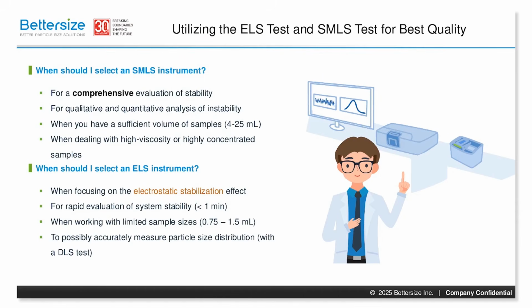SMLS is ideal when you have sufficient sample volume, typically 4 to 25 milliliters, and when dealing with high viscosity and highly concentrated samples. On the other hand, ELS is the preferred choice when you focus on electrostatic stabilization. It's perfect for rapid stability evaluations, often requiring less than a minute. ELS is also essential when working with limited sample sizes, as it only needs 0.75 to 1.5 milliliters.